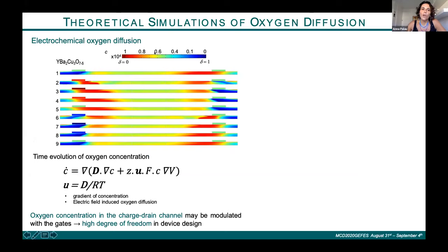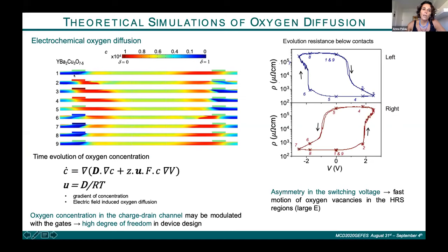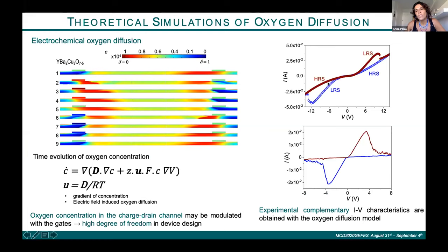We have also used theoretical simulation to see the oxygen distribution between one or two gates. For example, in this experiment we polarize one gate from the low to the high resistance state and the other in the other way, and here we obtain the loops. We obtain asymmetrical loops as we observe experimentally. This is the experimental hysteresis loop that we obtain, and this is the theoretical one, where we clearly see that we are able to modulate the oxygen distribution between those two gates, which gives us the possibility to design the kind of device that we want depending on the position of the gates.